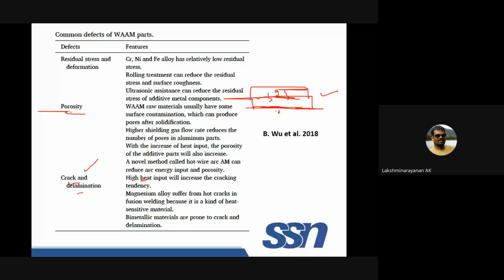Especially, cracks form when you are using two different materials, like copper here and then stainless steel here. These two are not an exotic combination. If I use stainless steel and titanium, it is very, very difficult to join. Similarly, magnesium and aluminum: magnesium melts at 650 and aluminum at 660, so the melting points are very similar, but unfortunately the crystal structures differ, FCC and HCP, and the solubility in each other is also not good. Because of that, whenever you consider two different materials, you need to check the feasibility. You have a lot of scope for research also.